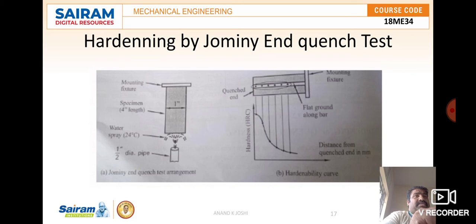As a function of position, the distance from the quenched end corresponds to a different rate of cooling, and this hardenability curve is plotted with hardness as a function of the position from the quenched end of the specimen. So it depends upon how the quenching is done. Here the hardness is highest, because it is quenched at this end, and it decreases moving along like this. So this is the hardenability curve we can see here, based on the cooling rate and the position at which you apply the cooling effect on that material. So this is about hardenability by the Jominy end quench test.